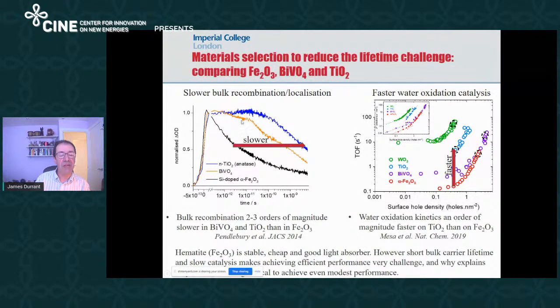And you can see that the charges generated in these oxides don't live very long. Titania is reasonably good. The carriers live for a few nanoseconds. For hematite, carriers live for a few picoseconds before they recombine. Those fast timescales are important when we compare them to catalysis. So these are timescales of catalysis. Catalysis is a little hard to quantify in terms of timescales. What we've plotted here, and I'll come to it later, is a turnover frequency, so 1 over lifetime,